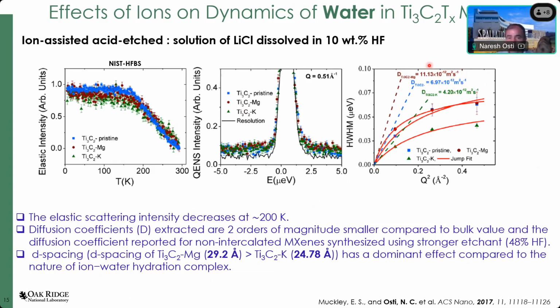It means that the water in all these three systems is in between the layers now. It is not in the stack. They are in between the layers. That's why there is a significant reduction in the water diffusivity. Another thing we found in this particular study is that the diffusion coefficient of the water in potassium intercalated MXene is smaller compared to that in magnesium intercalated MXene, which is quite interesting because the magnesium ions make a very tight hydration shell with the water molecules.